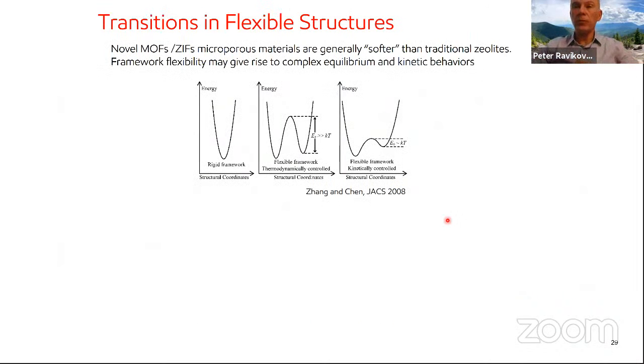Another important phenomenon which occurs in metal organic frameworks is the phase transition. So how can we understand this? If you look at the free energy landscape of, say, a porous structure along some structural coordinate, a rigid framework is going to have just one energy minimum, in which case the structure will be vibrating around some equilibrium position. It could happen that the structure has several minima. For instance, this is a bistable structure, which can exist either as one structure or as a different structure. If this free energy barrier is sufficiently high, it's not easy for the structure to jump from one state to the other unless there is some stimulus due to adsorption, temperature, or pressure.